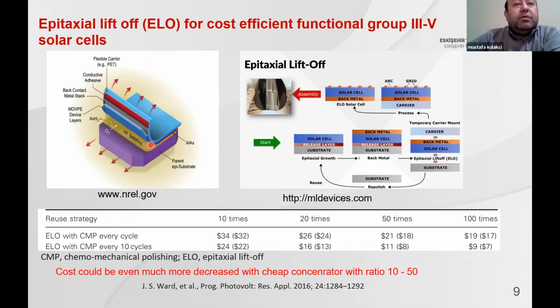Then after loss of aluminum arsenide, you can easily transfer these devices, when you look here, into the plastic carriers. When you look at the etch ratio between aluminum arsenide and, for example, gallium arsenide, the ratio is about 10 million times. Aluminum arsenide etch rate is much higher when you compare it to gallium arsenide. Gallium arsenide is almost not affected in these processes.